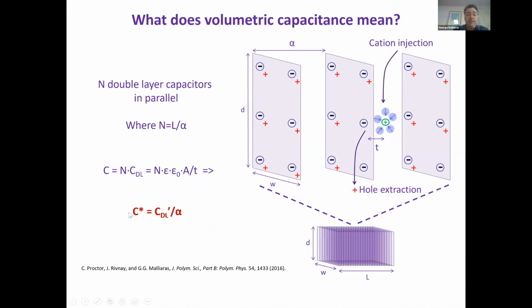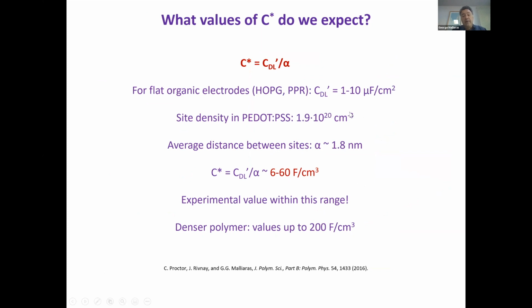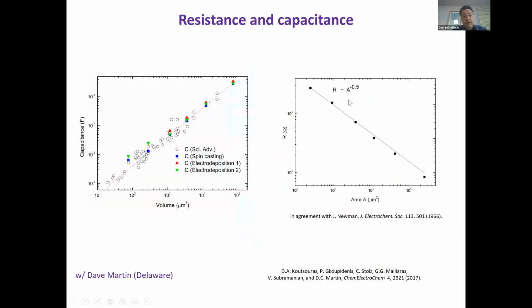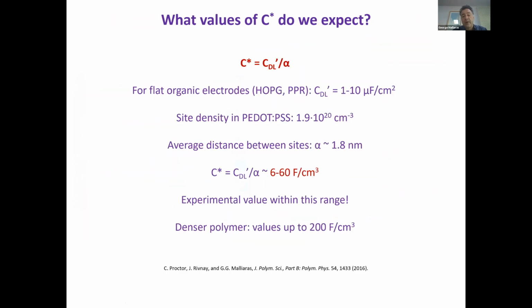And you can extract the volumetric capacitance of PEDOT:PSS to be equal to the capacitance of a double layer, which again has this fixed value of 1 to 10 microfarad per square centimeter, divided by the distance between the doping sites. So if you put the numbers down, again, 1 to 10 microfarad per square centimeter, you end up getting a capacitance per unit volume for PEDOT that should be between 6 and 60 farad per cubic centimeter. What we measured here, and I failed to mention, is 40. The slope here gives you 40 farad per cubic centimeter, which is within this range. So a very simple back of the envelope calculation gives you a quantitative prediction of what the capacitance should be.